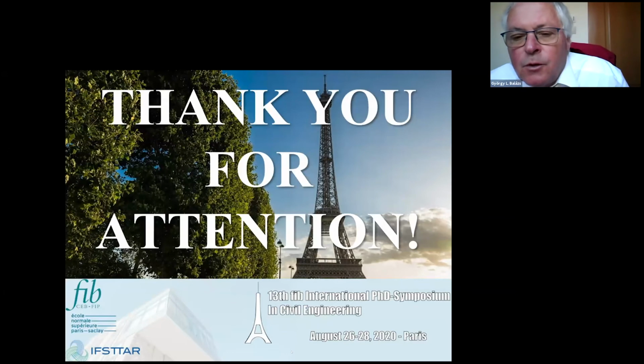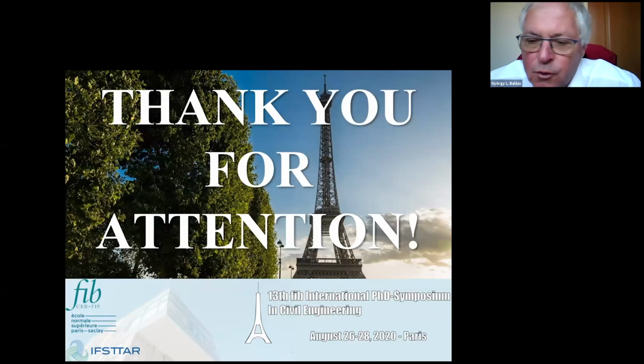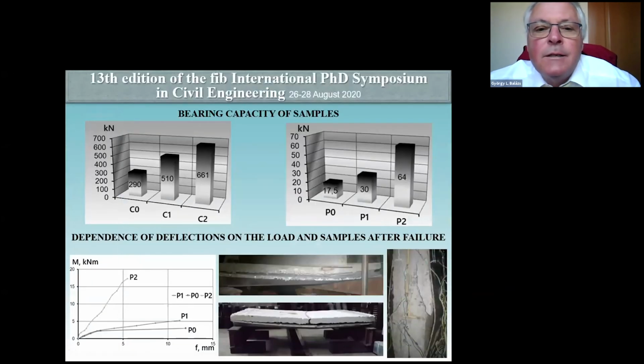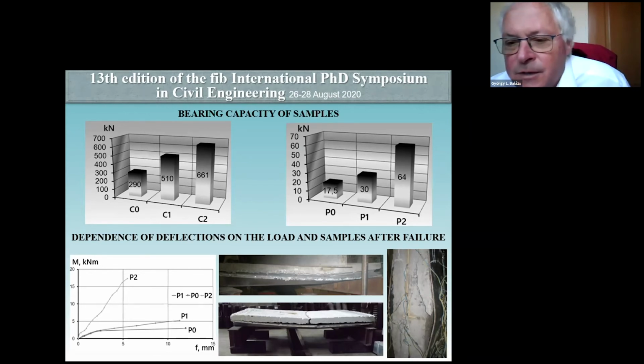Some small questions. We speak about force transfer in the longitudinal horizontal direction, and in one of the last photos there was a slab with a separation, a delamination in the middle. So we have to speak about force transfer transverse as well. Do you have experience? So force transfer parallel to the steel and force transfer perpendicular to the steel. In this case, for example, the filler size could be very important. So do you have an opinion about these transverse stresses?